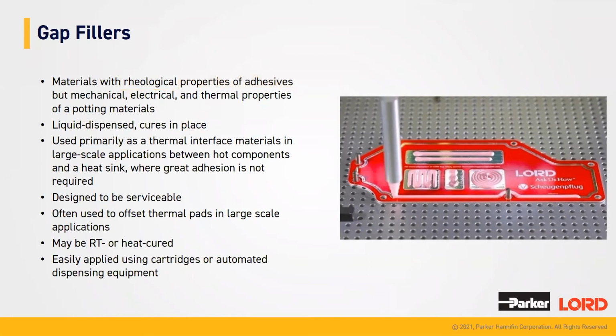Now, gap fillers are liquid dispensed, and they do cure in place, and they're used primarily as a thermal interface material in large-scale applications between hot components and a heat sink, but where you don't necessarily need any great adhesion. It's really more to be used as a thermal interface material than a structural adhesive.